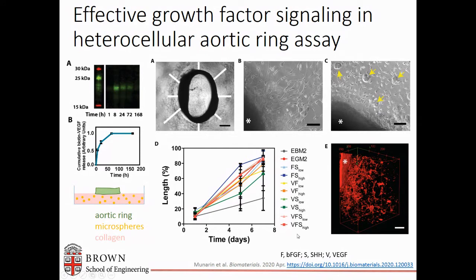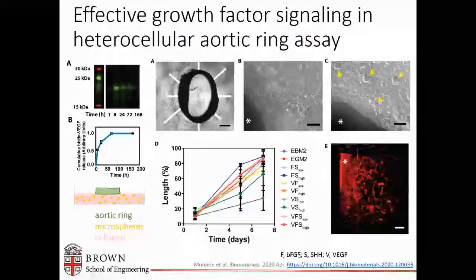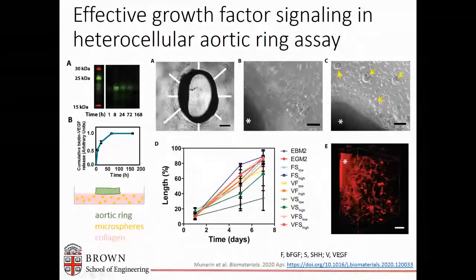So we loaded these microspheres with different combinations of basic fibroblast growth factor, sonic hedgehog, and vascular endothelial growth factor in dual and triple combinations at low and high concentrations. And we compared these to a negative control, so a basal medium stripped of those growth factors here in gray, or positive control, a complete medium that had all of those growth factors in it. And you can see that a number of groups were performing just as well as the positive control. And that included a dual combination of FGF and sonic hedgehog, as well as some of these triple combinations of VEGF, FGF, and sonic hedgehog at high concentration, which is the group that we ended up using.